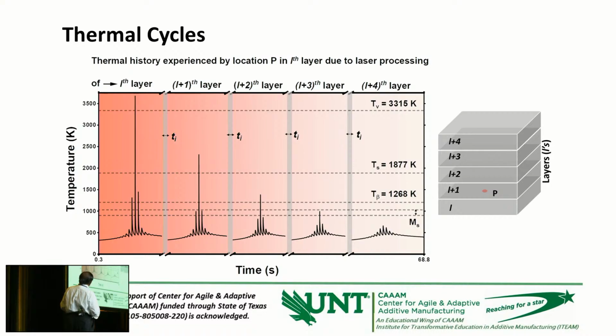So this point, in this layer, sees the rise in temperature multiple times, and the magnitude of that temperature rise could be as high as to cause remelting here, or sometimes not melting, but as high as to cause the phase transformation, solid state phase transformation. So how far these effects are valid can be predicted by this computational model.